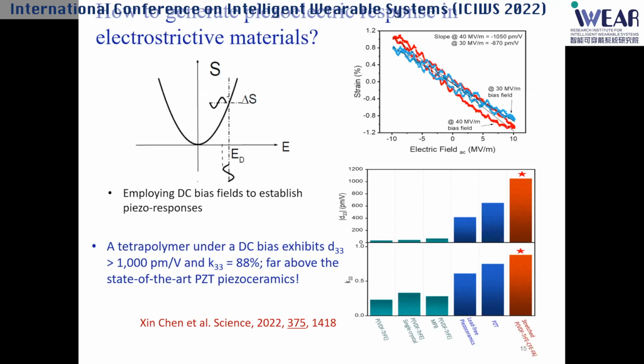It's very simple. For this tetrapolymer, we find if we apply, for example, a DC bias field of 30 megavolts per meter or 40 megavolts per meter, we can generate piezoelectric coefficients of about 1,000. The PVDF-TrFE is about 30 to 40. This is 1,000 - many, many times larger than that.